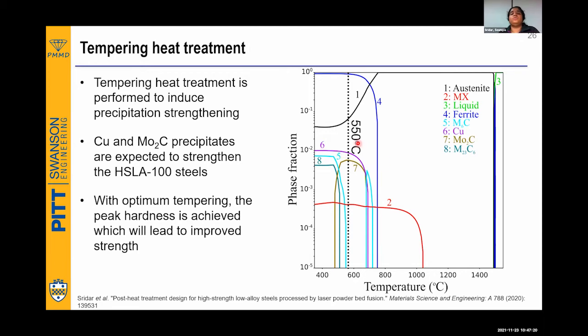And so we choose a temperature of 550 degrees C as the tempering temperature. At this temperature, what we expect is copper and Mo2C precipitates will strengthen the HSLA 100 steel. And how we are going to figure out the optimum tempering time is by finding the peak hardness.